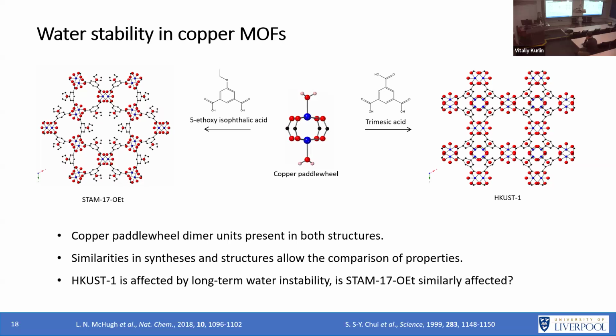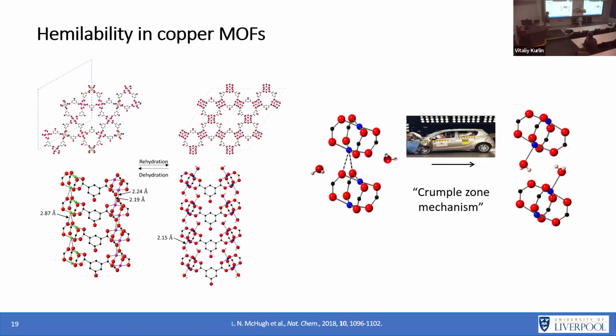So they've got the same copper paddle wheel structure. The linker and the way it's coordinated is a little bit different. Is that also going to be similarly affected by water? The answer was no. It led to a completely different mechanism, and quite a cool mechanism actually, called the crumple mechanism, but it was talking about this thing called hemilability in materials. So hemilability is essentially where you've got these sort of sacrificial bonds within a structure.